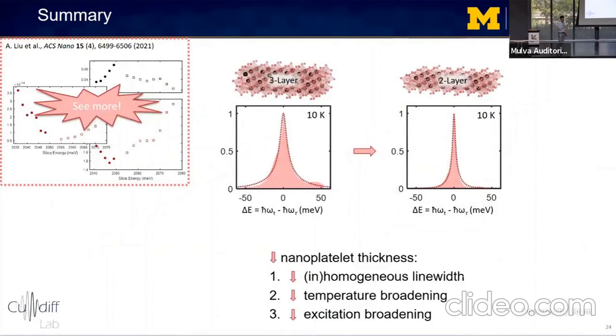So to summarize this part of my talk, we applied 2D spectroscopy at cryogenic temperatures to colloidal nanoplatelets to measure their intrinsic line widths and line broadening mechanisms. And we find that decreasing nanoplatelet thickness comes with a host of beneficial effects. So for example, decreased homogeneous and inhomogeneous line widths, decreased exciton-phonon coupling, as well as decreased excitation-induced dephasing.